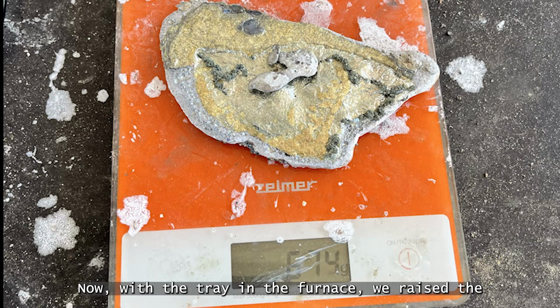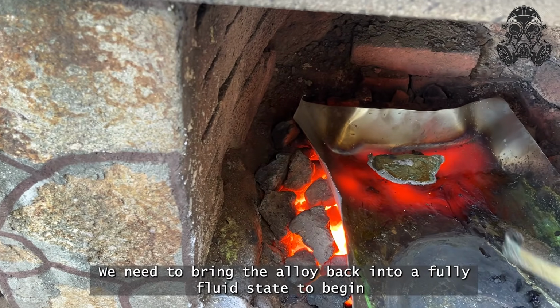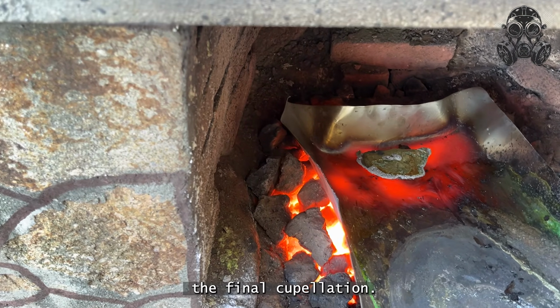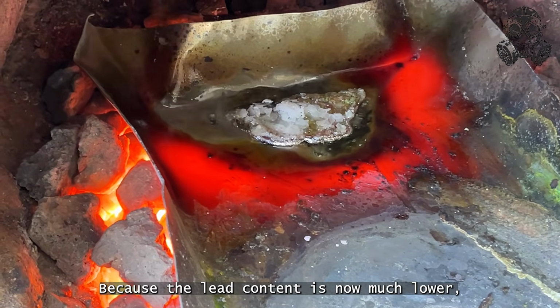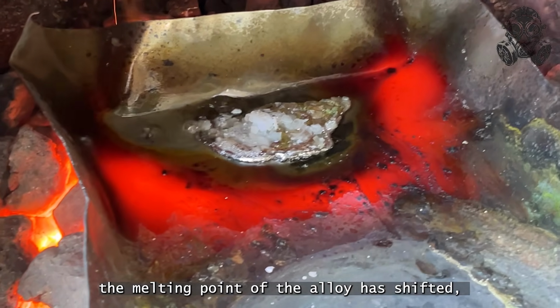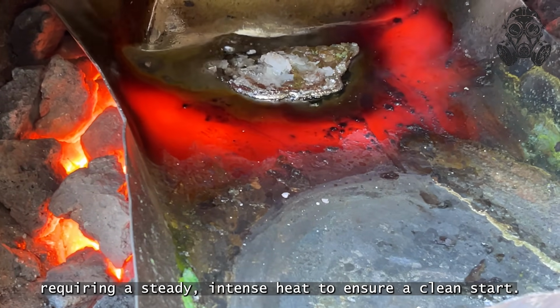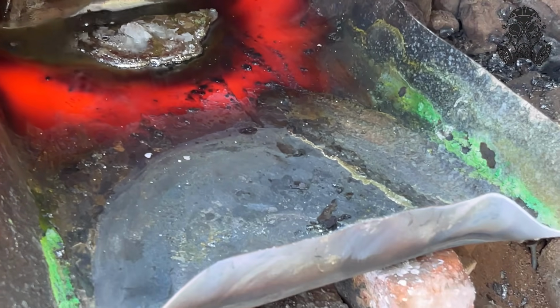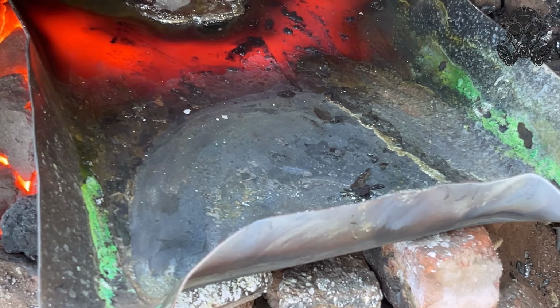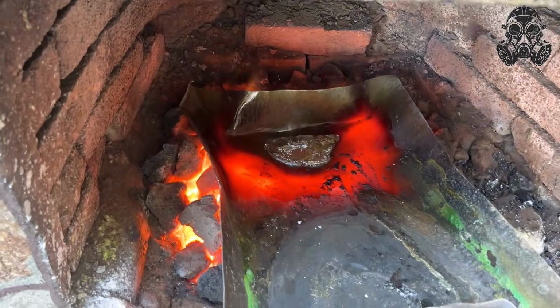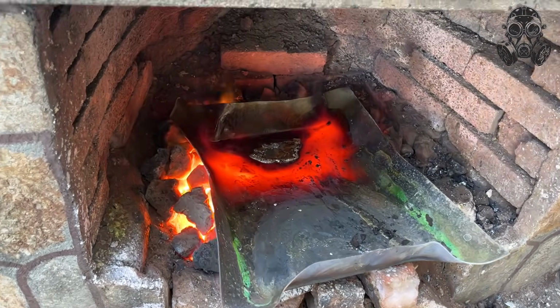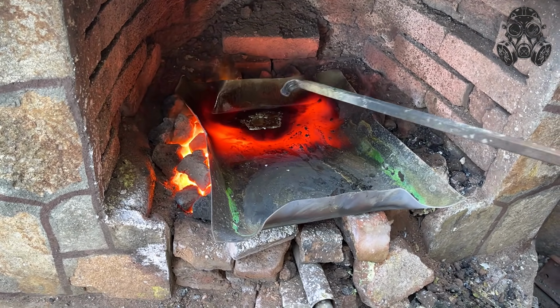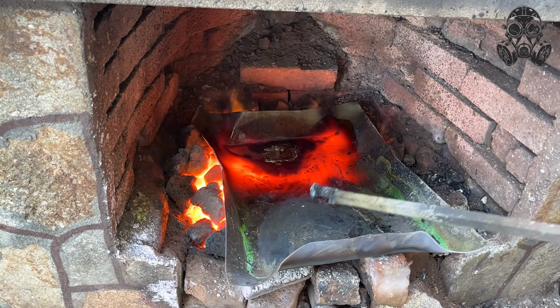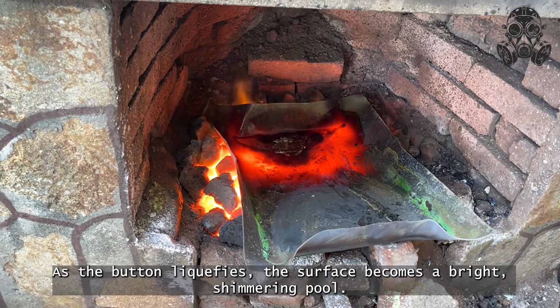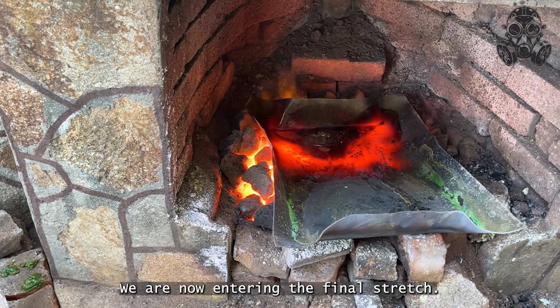Now, with the tray in the furnace, we raise the temperature to remelt the metal. We need to bring the alloy back into a fully fluid state to begin the final cupellation. Again, we added the flux. Because the lead content is now much lower, the melting point of the alloy has shifted, requiring a steady, intense heat to ensure a clean start. As the button liquefies, the surface becomes a bright, shimmering pool. We are now entering the final stretch.